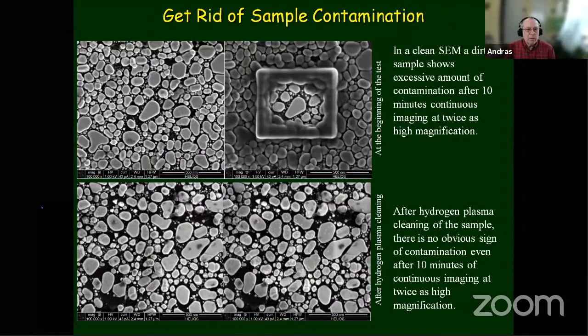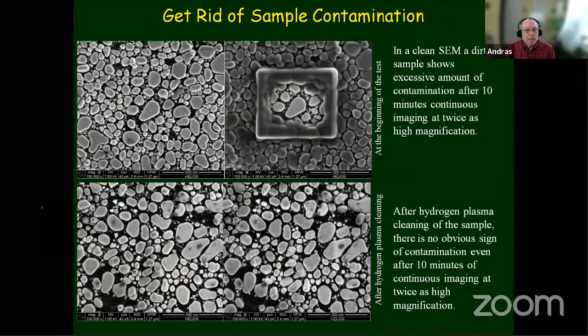Next slide, please. Very good. So this is, just please go back one, somehow I jumped two. That's about the sample. This was a sample that has been in storage, not used for years. The first image that you see is on the upper left. But if you dwell on the sample for 10 minutes, at twice as high magnification, in this case 200,000 times magnification at 1 kV accelerating voltage, you will see a really ugly pattern forming due to the sample problem.